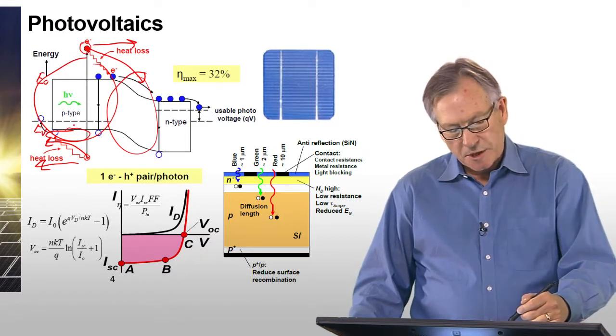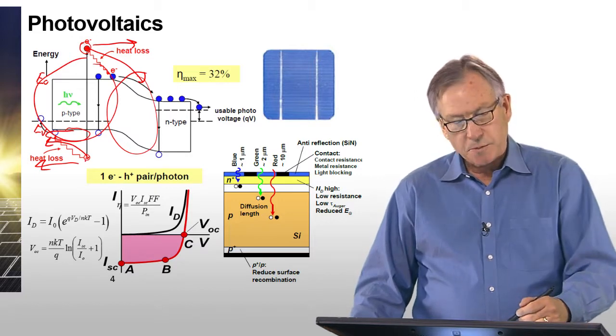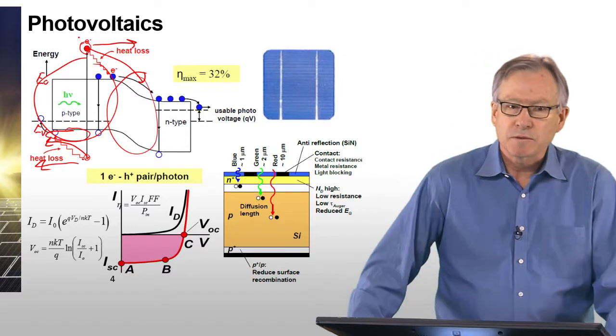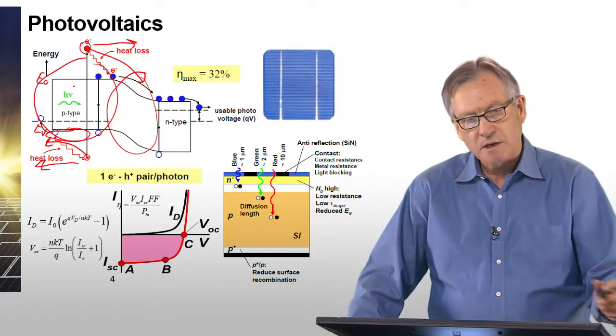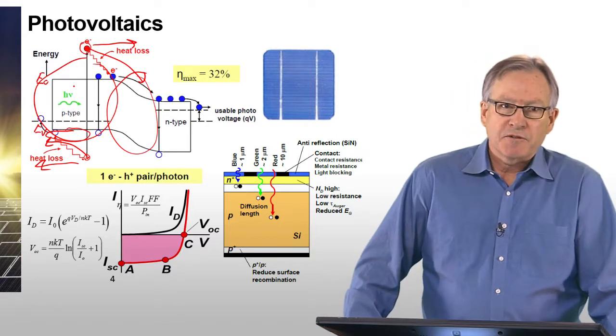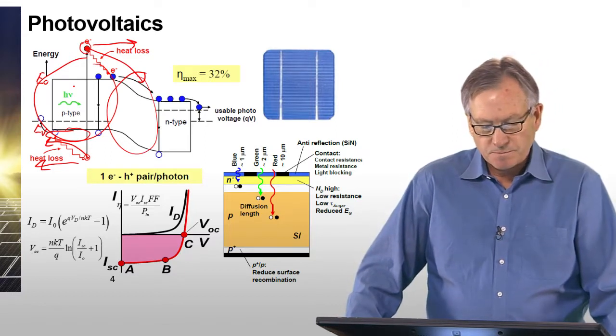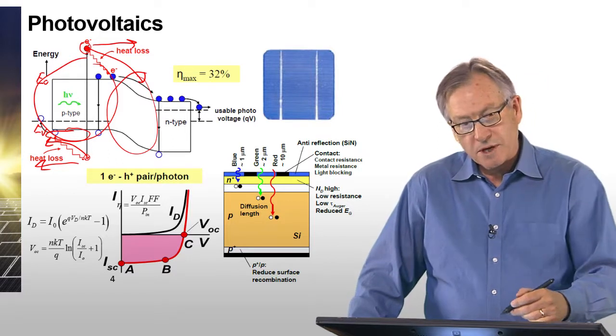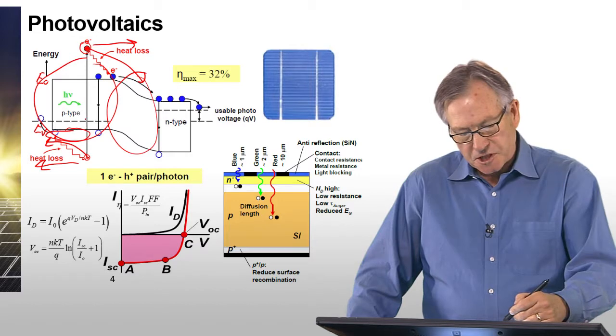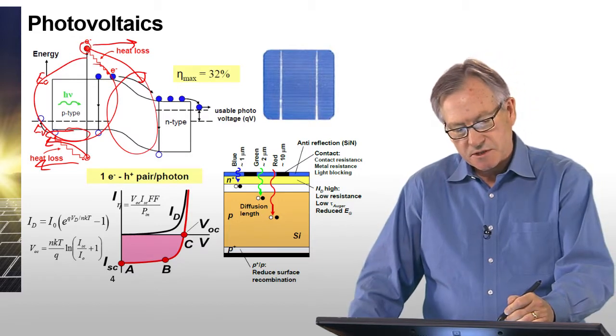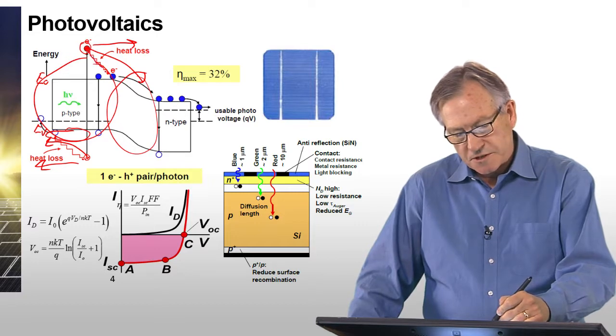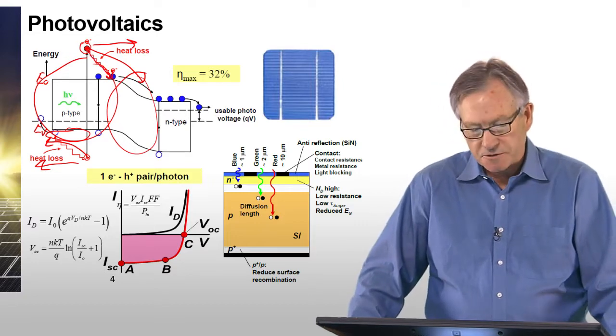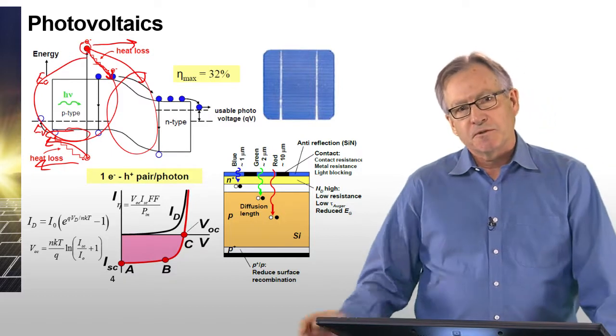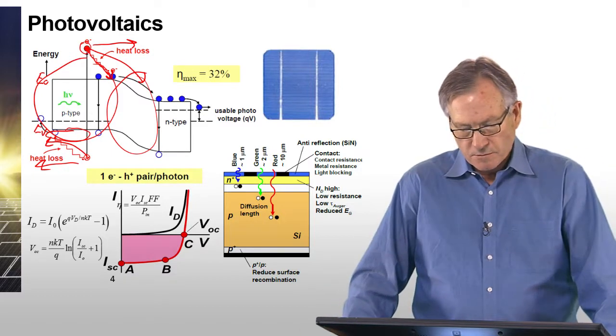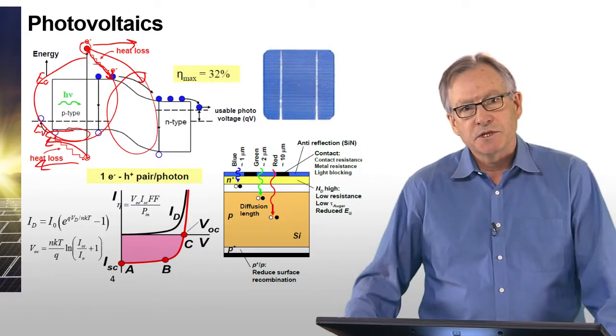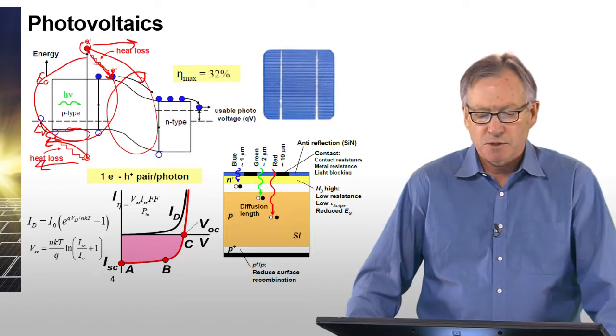So what you can see about this process is that photons, I should say, that have an energy greater than the band gap are able to promote an electron from the valence band to the conduction band. However, if the energy of the photon is less than the band gap, you can't have any absorption, and therefore the semiconductor is transparent. Another issue is that when you create an electron-hole pair, it has a certain excess energy above the band gap, and what typically happens is that the electron or the hole quickly loses energy and relaxes to the band edge. It goes to the lowest energy state, and so you lose all the extra energy of the photon into producing heat. So these are two losses, and I'll talk about how these lead to the maximum conversion efficiency of a solar cell.